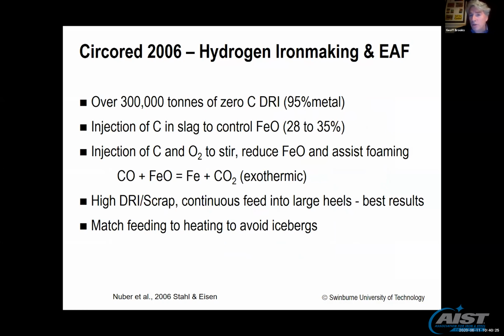And they reported that they had to inject carbon into the slag, so that problem that has already been brought up in the Q&A section of this talk about what would happen with the FeO. They had to inject carbon to keep the FeO at a reasonable level. I would describe 28 to 35% as relatively high FeO, but not unacceptable depending on your slag volume. They also had to inject carbon and oxygen to keep the FeO down, but also to assist foaming. So they found it necessary to have some carbon and oxygen coming into the system.